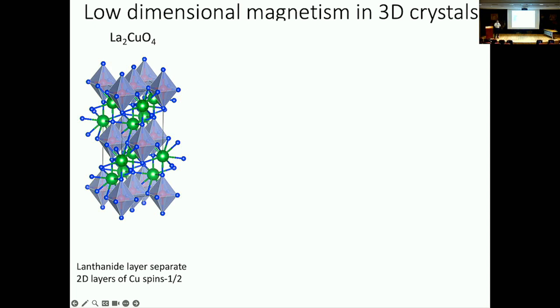So the first material is lanthanum copper oxide, which is the parent compound to the copper oxide superconductors. We're not going to talk about superconductivity, but we're interested in the two-dimensional character of the magnetism in the system. And if you think back to these interactions arising from virtual charge hopping or electron hopping, then what really happens in this case is the lanthanum layer essentially precludes electron tunneling between the layers, and you end up therefore with a quasi two-dimensional magnetic material. It's a fully three-dimensional chemical substance. You can hold it in your hand, but the magnetism essentially has to do with individual layers interacting with each other. And that's a very interesting aspect of these materials, because when you go to lower dimensions, you enhance quantum fluctuations. And so chemistry can actually produce virtually lower dimensional magnetic materials.